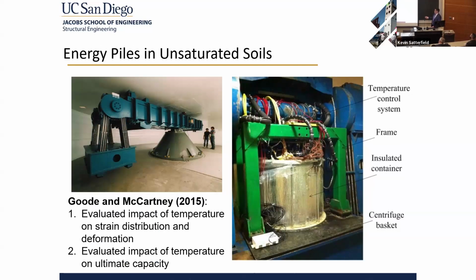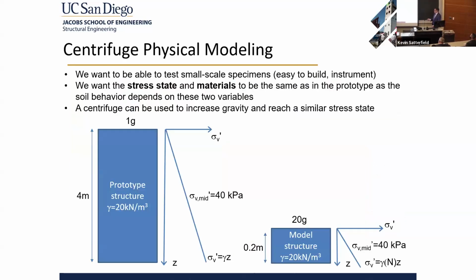So in this case, we have a tank with an energy pile in the middle of it. And the reason that we like to use centrifuge modeling is that we can scale the stress state. So we can have a reduced scale model that has the same stress state as in the field, in the prototype. And we can scale things like time and other variables to have similitude between the two.